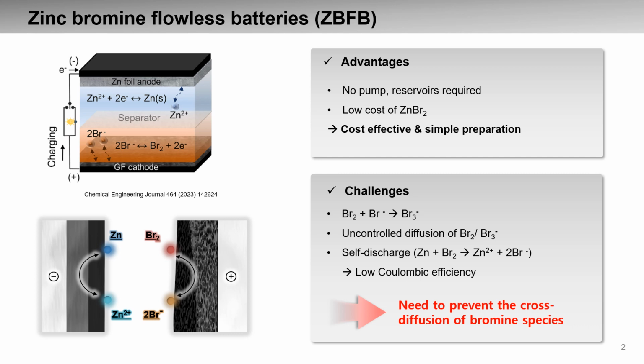These species are soluble in the electrolyte, so they can diffuse from the positive electrode into the bulk electrolyte, driven by concentration differences. Further, they can directly react with the negative electrode by cross diffusion, leading to self-discharge and low Coulombic efficiency. Therefore, in this flowless system, it is very important to prevent the cross diffusion of corrosive bromine species.